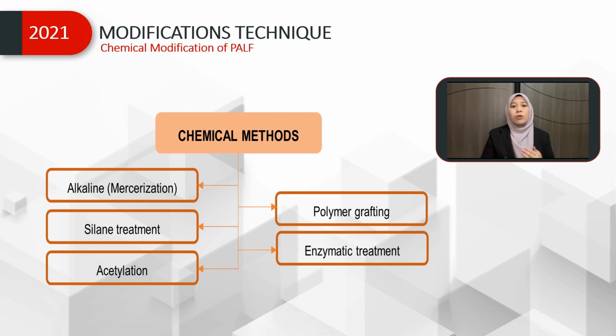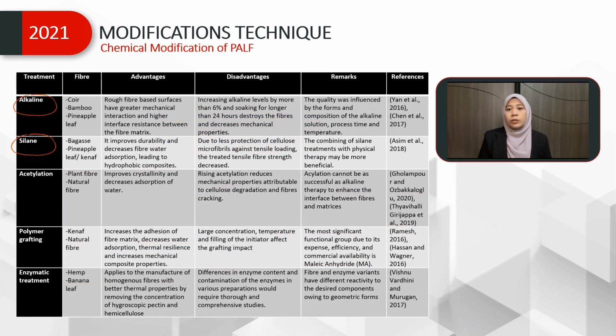Modification technique of chemical treatment: modifying the surface of PALF has been conducted by various methods such as alkaline treatment, silane treatment, acetylation, polymer grafting, and enzymatic treatment. The use of chemical reagents for modifying the fiber increases the mechanical properties and resilience of the fiber-reinforced composite and enhances the adhesion between the surface of the fiber and the polymer matrix by minimizing the water absorption of the composite. From the table, we can see that treatment under alkaline and silane treatment is the best. This is because alkaline treatment gives a rough fiber-based surface that has greater mechanical interaction and higher interface resistance between the fiber and matrix, while silane treatment improves durability and decreases the fiber water absorption, leading to hydrophobic composites.